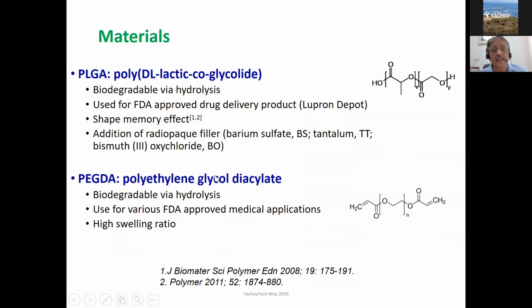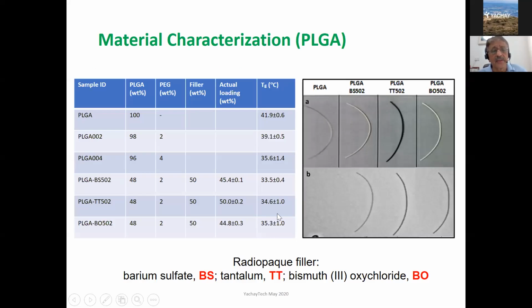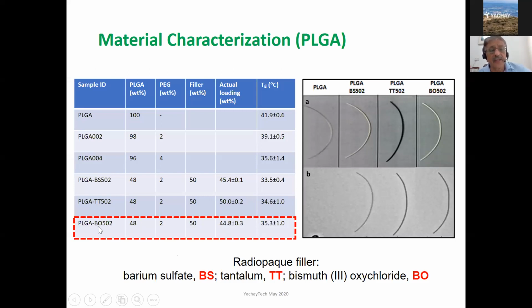Okay, so these are the polymers that are used in this application. Poly lactic-co-glycolide, PLGA, a copolymer that can be filled with radio-opaque fillers like barium sulfate and so on. And then the polyethylene glycol diacrylate, which is the hydrogel that swells to plug the artery. Okay. I won't go into all the details of the evaluations we did to evaluate the radio opacity under X-ray, as well as the mechanical properties and self-expansion or shape memory properties. But this is the composition we ended up with.